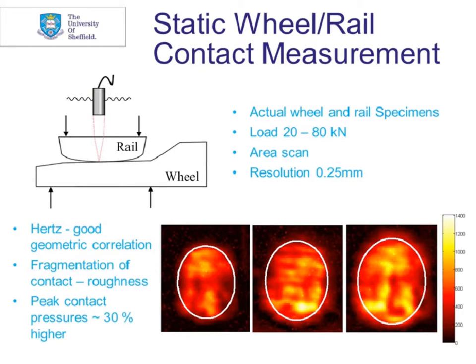In the first instance, we did some very simple scans of a static wheel-rail interface using a focusing transducer. You can see the results here. Should note that this is not a run-in wheel-rail surface. This is quite a new wheel against a new rail, so it's not a nice smooth surface on the components, which is why it looks quite fragmented. If you compare to Hertz, you get quite good correlation. Obviously, the real contact's slightly bigger because of that roughness. And the peak contact pressures are much higher because of that roughness as well. And this information on its own is very useful to start validating models of interfaces.